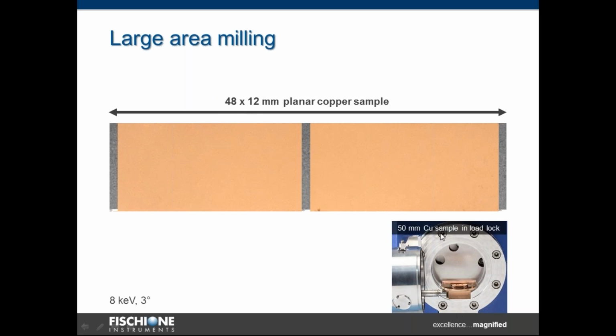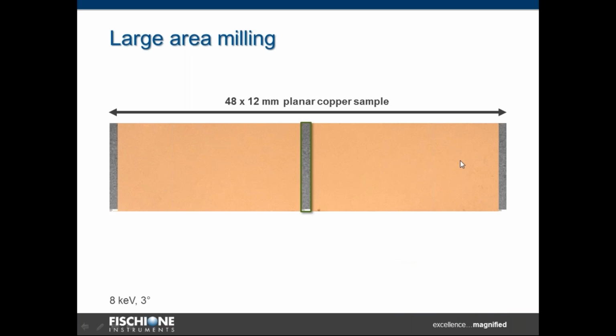Here you can see the load lock of Model 1062 with the sample sitting on the stage after the milling process. Once again, we collected a lot of SEM images and EBSD data for the whole area of that sample. You can see examples of images collected in the center and at the edge. If you zoom in on the images, you will see extremely clean and uniform milling over the whole area, and you can easily distinguish the microstructure of the copper.